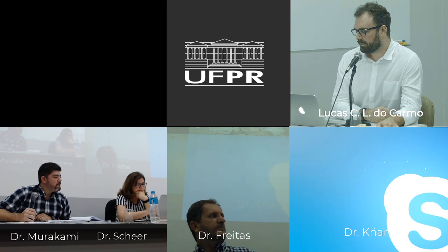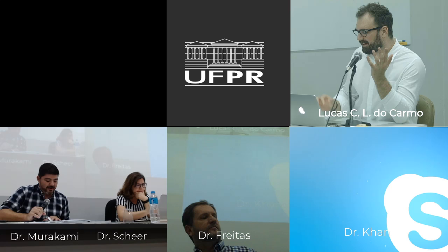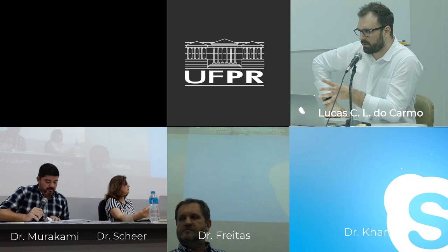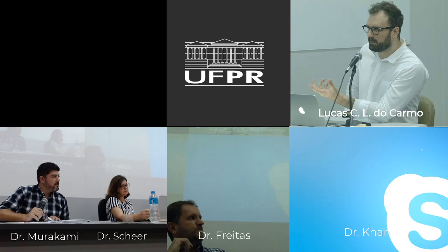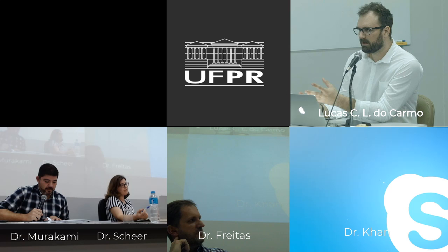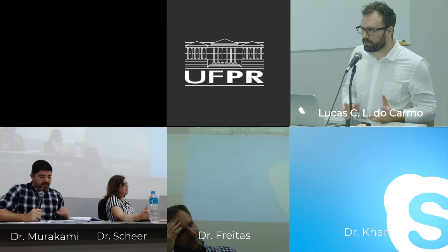But you can see that E is missing, and then G, H, and I are not in order of oil concentration, because when I was homogenizing G, which is the one with approximately 70% oil phase, it separated phases before I could complete homogenization. And then I had to correct H and I, which would be 80 and 90%, to have lower oil concentrations, because I thought that maybe 70% is the limit that this emulsifying system can accept. So I had to reformulate them, because otherwise I would lose these formulations.